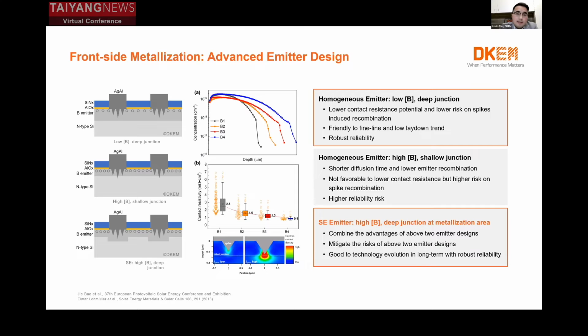Because this kind of design will give us lower contact resistance potential and a lower risk of spike recombination. It's also friendly to fine line and low laydown trend. The other quite important thing is that this kind of deep junction gives us robust reliability. For the high surface concentration shallow junctions, most of its performance is opposite, but it also has some benefit on the diffusion time and also a lower emitter recombination.